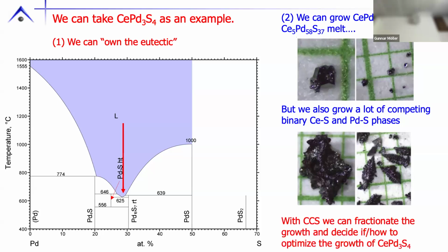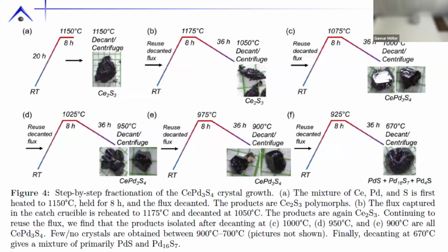Well, we can fractionate. And what I mean by that is we can take our initial composition, heat it up to 1150, stay there, and see if we even are in a single phase liquid regime. We were not. Okay, so we got rid of this, and then we reused the decant. We heated up a little more, 1175, cooled down to 1050, still had this wrong binary phase. Get rid of that, reuse the decant. Now we heat up to 1075. You'll note that I'm heating up to a little above the decant, but each time I cool lower.